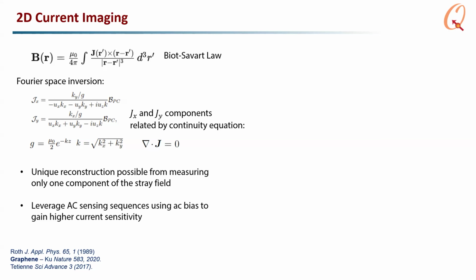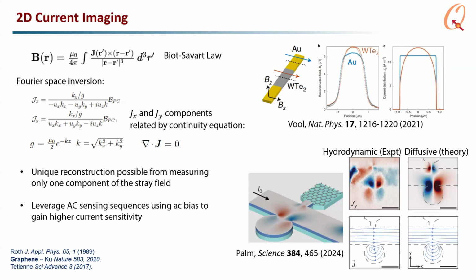So 2D imaging is completely unique, and people have done really beautiful work imaging hydrodynamic flows in both WTe2 and graphene at room temperature, where they see the effects of viscous electron flow. For example, when they make these pockets on the side of a graphene channel, you can see a counter-rotating whirlpool due to hydrodynamic effects, whereas if it was purely diffusive transport, the whirlpool would be in the same direction as the current. So this has really revealed a lot about electron scattering in these devices. So by imaging the stray field, you get the vector current profile.